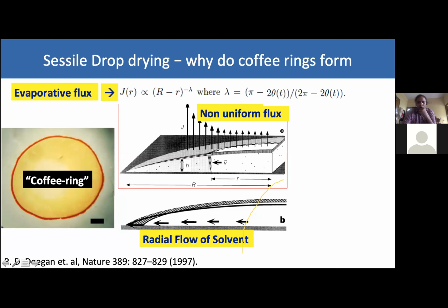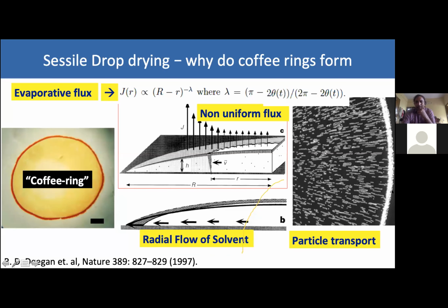And this fluid flow carries the particles that are dispersed in the fluid, and it deposits the particles at the edge. Therefore, there is a particle transport which is mediated by the capillary flow arising because the fluid that is evaporated at the drop edge has to be replaced by the fluid in the interior, to ensure that the contact line is pinned during the evaporation process. Therefore, the mechanism of formation of the coffee ring is fairly well understood, and it is known that this capillary flow is what leads to the deposition of particles at the edge.